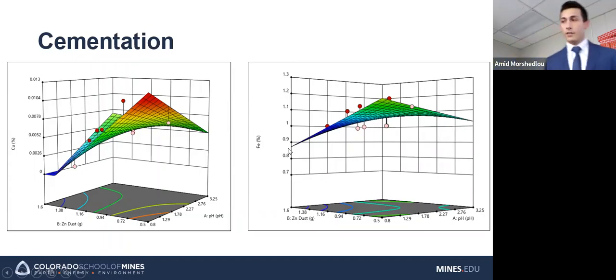And so on the iron side of things, what we can see is, generally speaking, as we increase the pH, we'll drop more and more iron out of solution. And that, for the most part, is what we expect based on the Eh-pH diagram. And same thing, as we put in more zinc dust, more iron drops out of solution. This is what we would expect because, right, zinc is what's dropping iron out of solution. Huge surprise. So again, what we can do is take these diagrams and help us better inform what sort of processing conditions we want to use to get the results that we want.